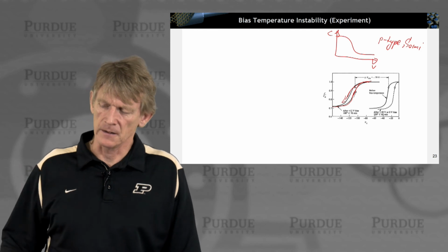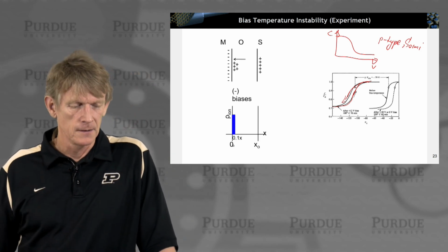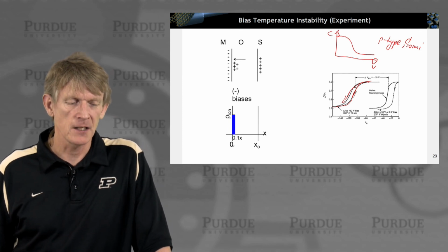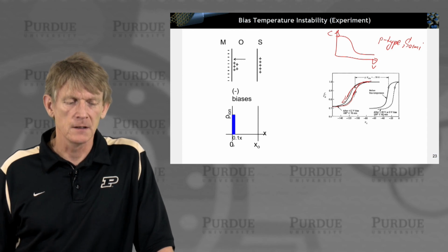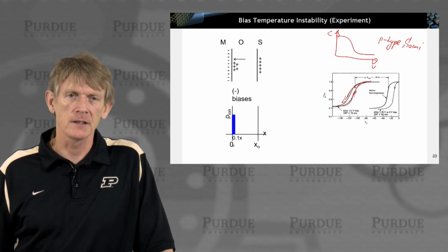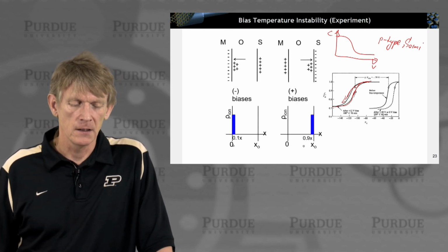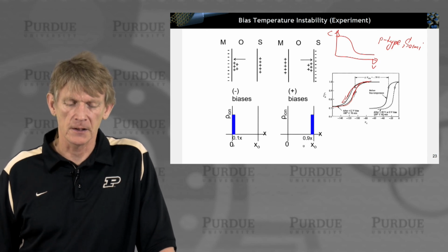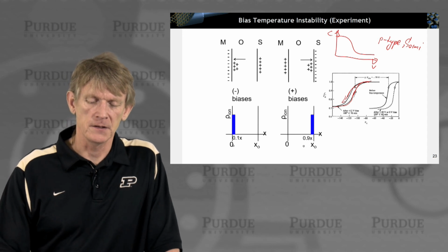Okay, I was just thinking, is sodium positively ionized? Yeah, it is. So you have a bunch of positive charges that might be sitting at the MOS interface, and maybe they start out at the metal interface, and after a certain time, these charges have migrated over to the semiconductor side, and they will have shifted the behavior of your CV curve.